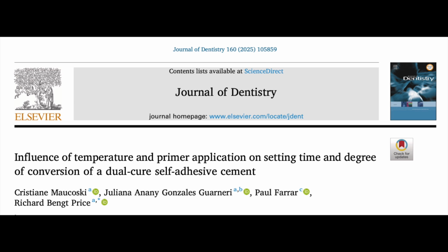Well, the big factor, according to the paper, was temperature. No surprise there, really. Much faster at body temperature, 37 Celsius, compared to standard room temp, 23 C. Significantly faster. And using the primer also gave it a boost, sped things up noticeably. Which is good clinically, isn't it? Once it's placed, you want it to set efficiently. Helps the workflow, definitely. And it's worth noting all the conditions they tested were still well within the ISO standards for these dual cure materials.